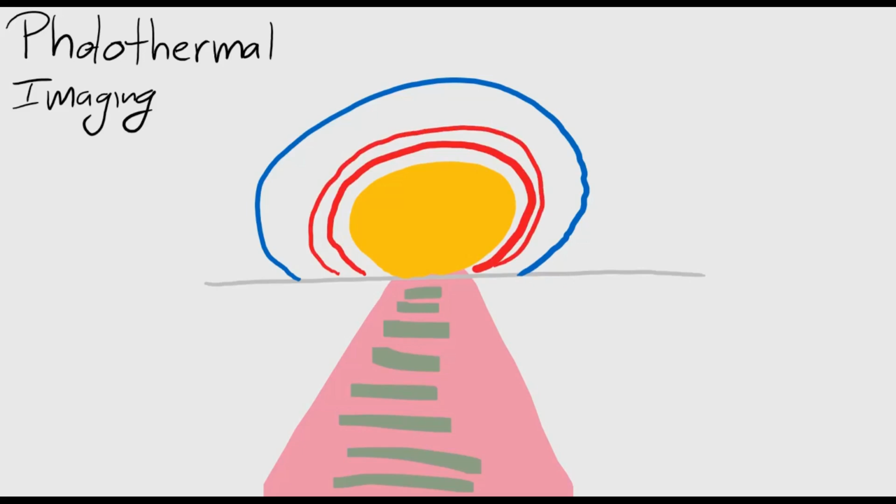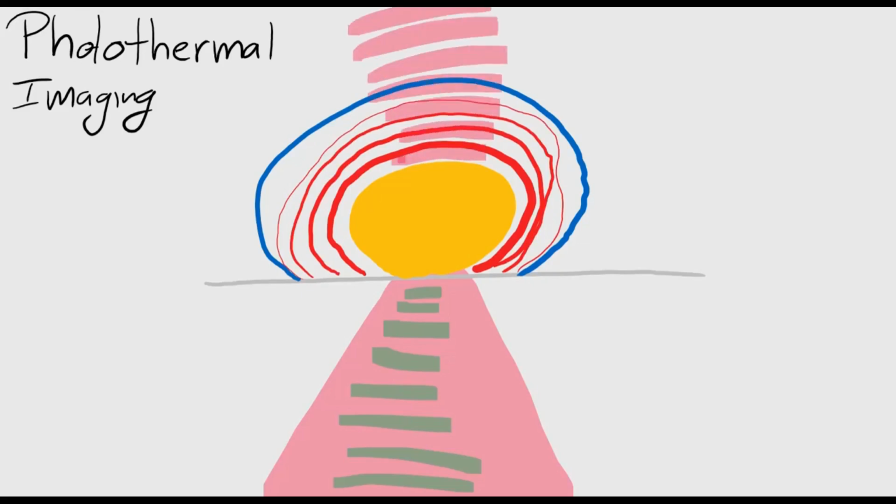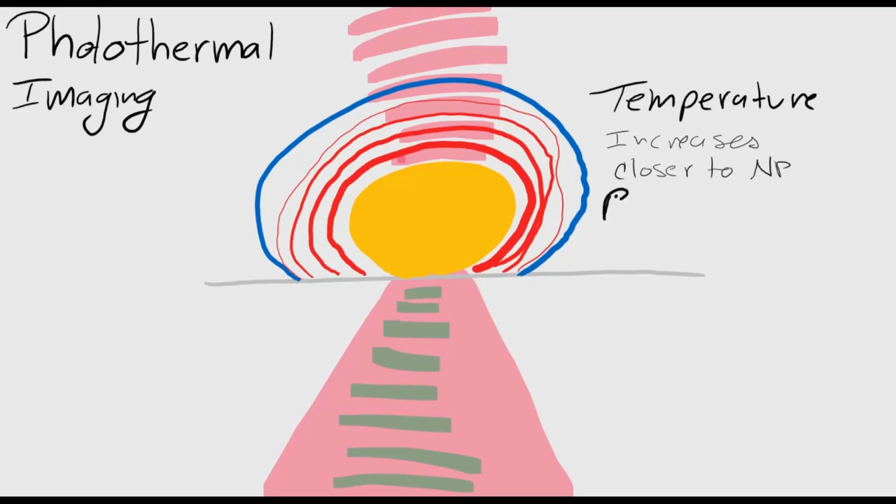red circles. Since the refractive index of the embedding medium is temperature dependent, an increase in temperature causes a decrease in the local refractive index and thereby creates a corresponding refractive index gradient. The probe beam, shown in red, is then scattered by a change in refractive index and results in the photothermal signal, thus allowing for pure absorption information of individual nanoparticles with sizes of only a few nanometers to be detected.